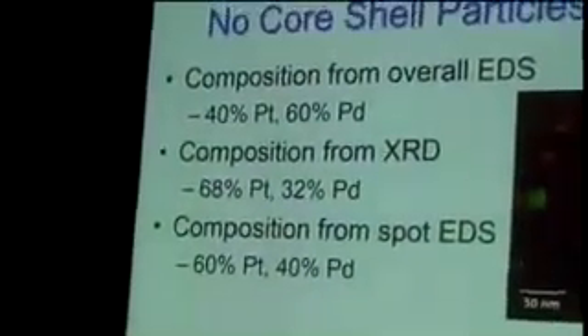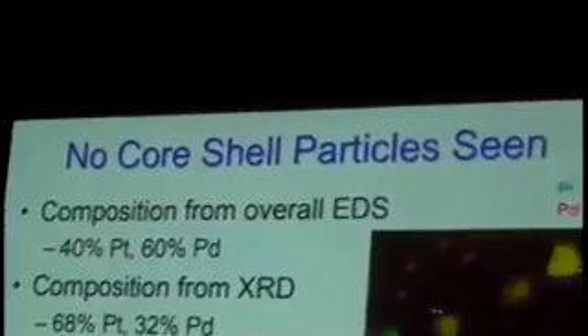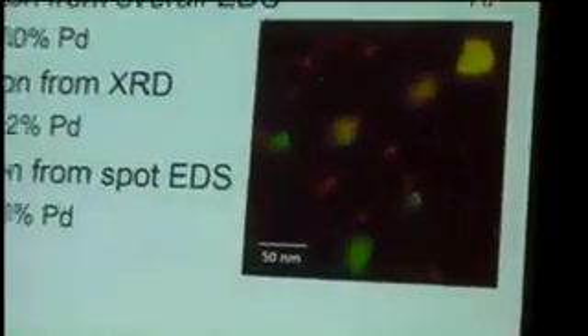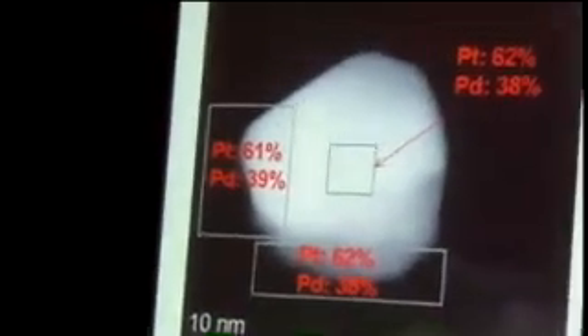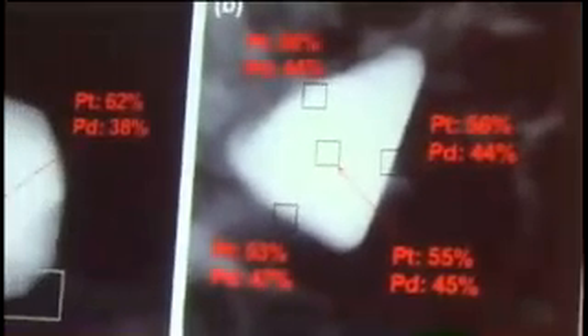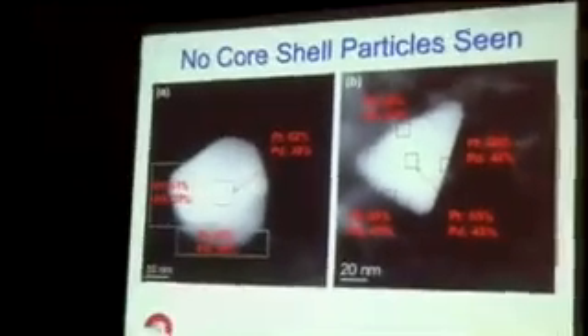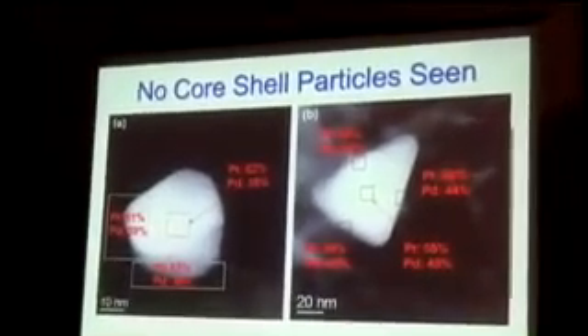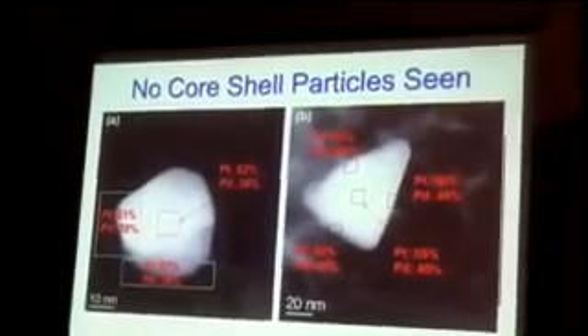And these are energy dispersive spectroscopy maps that allow you to see the dispersed phase is mostly palladium, and the metallics have both platinum and palladium. What about a core shell structure? Do we see a core shell structure? We don't. Everywhere we look at these particles, the composition is nearly the same. And this is confirmed by EXAFS, because the coordination number of platinum neighbors to palladium and palladium neighbors to platinum are the same. So it doesn't make this problem.